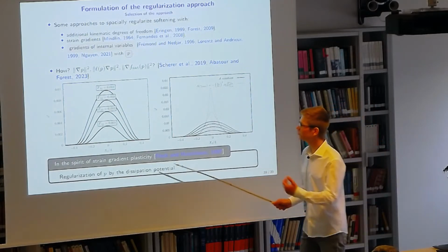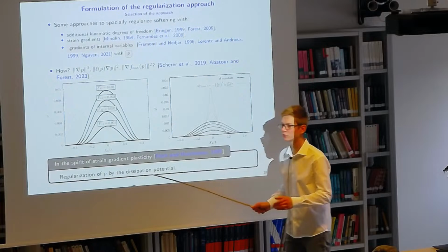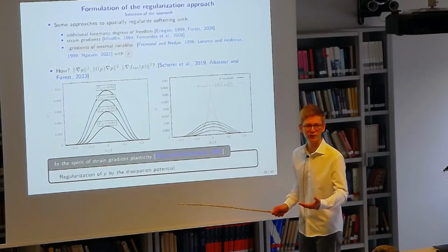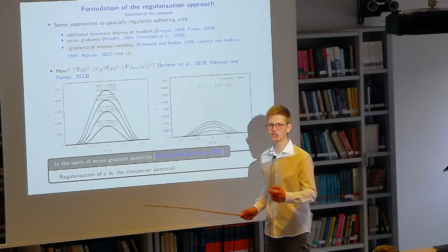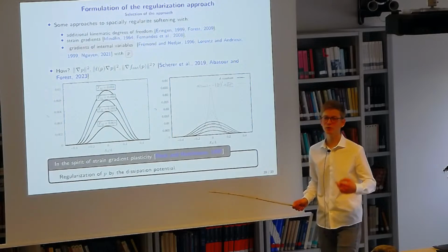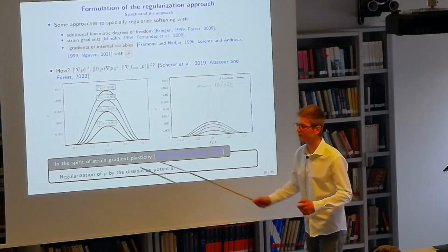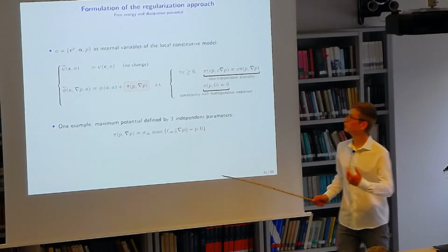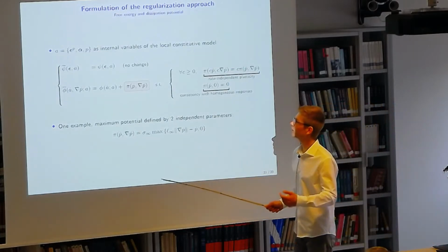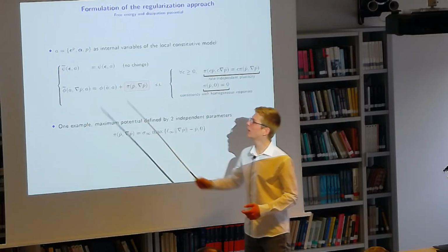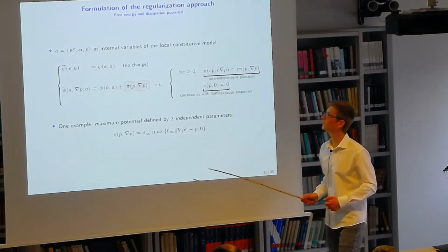Our approach, which is going to be presented, was quite different. We tried to explore the possibility of introducing the gradient of the cumulative plastic strain, no more in the free energy, but in the dissipation potential. By making this choice, we have some constraints about the way it must be involved. So, in order to be quite general, we consider alpha as a tuple of internal variables, which includes as one of them the cumulative plastic strain.